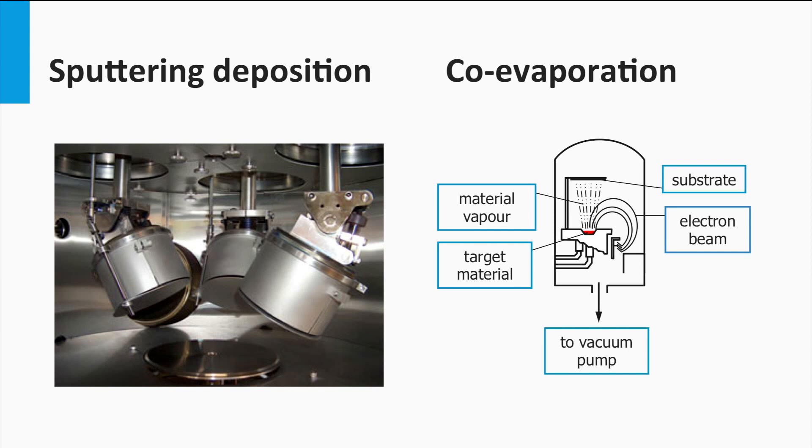One of the processing techniques is co-evaporation or co-sputtering under vacuum conditions. Using various targets of copper, gallium and indium, the precursors in various steps are co-evaporated onto a substrate. Two approaches can be used. First is the sputtering and co-evaporation on a substrate at high temperatures. During the process there is an additional selenium source and during deposition, a CIGS film is formed.